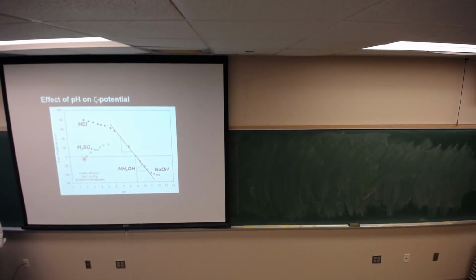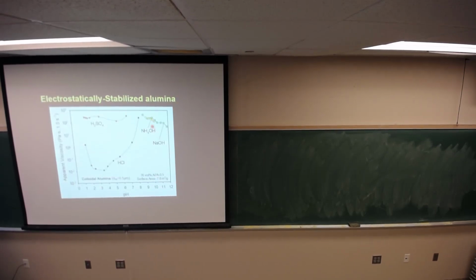Okay? So I bring in sulfuric acid, I bring in a divalent counter ion, that compresses the double layer. And it's even evidenced in the low volume concentration suspensions that make up the zeta potential data. These behave fine. So we are left to an inescapable conclusion that this shallow decrease in viscosity is due to the corrosion of the particle surface. Which means I'm putting aluminum 3+ ions in solution that are compressing the double layer.